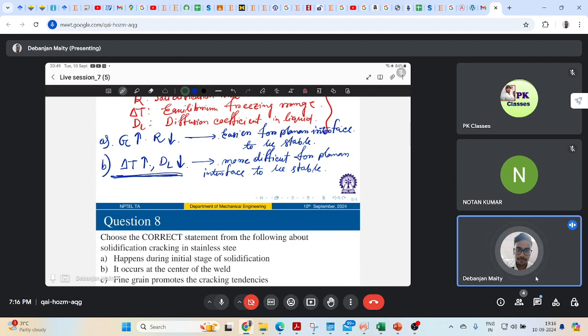when tensile stresses will be generated, tensile residual stresses will be generated at the center of the weld metal. You know? So solidifying weld metal will tend to contract, as I was talking. It tries to contract because of solidification shrinkage and thermal contraction.